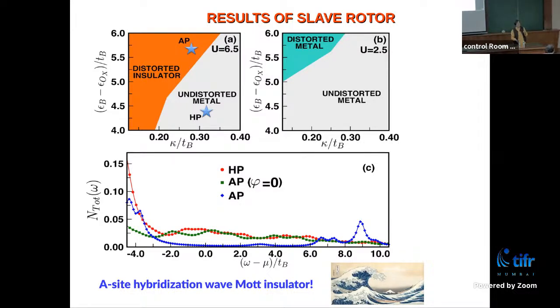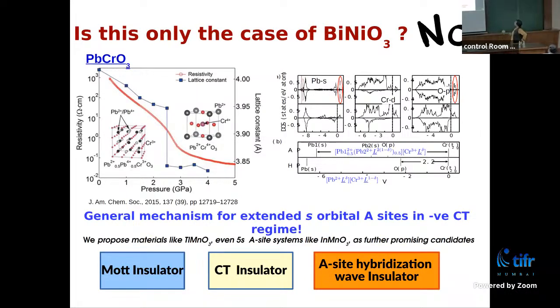But in addition, I need this hybridization between bismuth and oxygen to set up a hybridization wave, because I will have a big, small, big, small, some with 2 ligands, some with no ligand, 2 ligand, no ligand. That's a hybridization wave. And is it only the case for bismuth nickel oxide? No. Lead chromite, for which the same Japanese group did a lot of experiments. Here it's the same thing. You do not have lead 3+, instead you have lead 2+ and lead 4+, that's what they believe. But in our picture, everything is lead 2+, and everything is chromium 3+, only the ligand hole, which was associated with lead, putting pressure, now goes close to chromium.